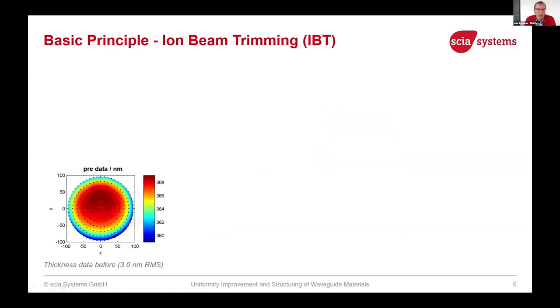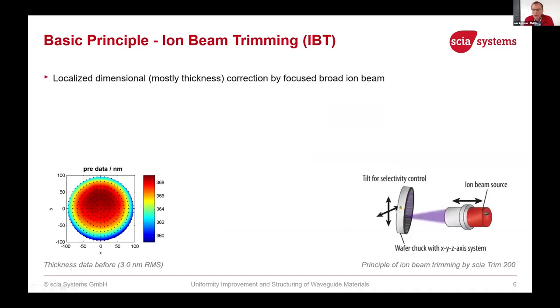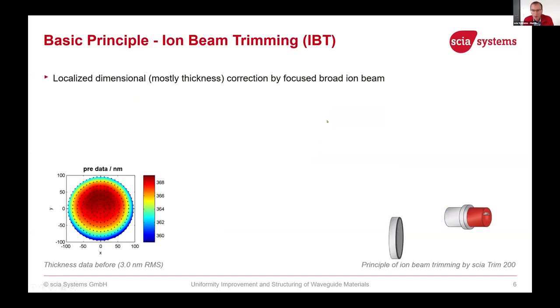A short introduction on the principle of ion beam trimming. Imagine you have a wafer, let's say a 200 millimeter wafer with a certain film on it, and the film has a thickness variation. The thickness variation can be pretty low. Here in the example, you have a variation from 368 to 360 nanometers, so just 8 nanometers variation. Sounds pretty smooth, but nevertheless, it may not be sufficient for your application. And therefore, we developed the technology that is called ion beam trimming.